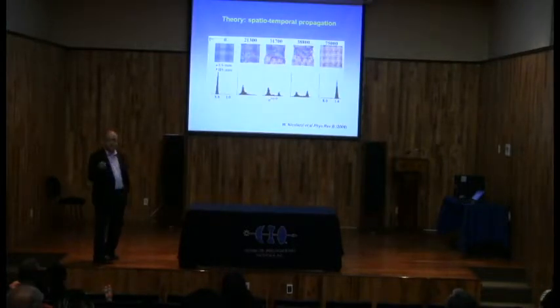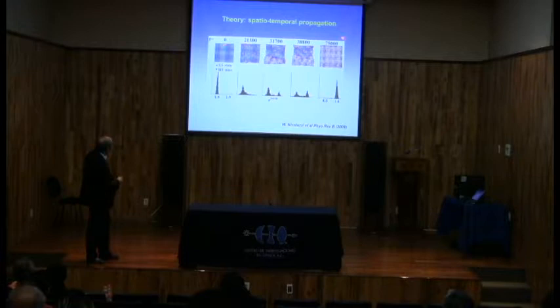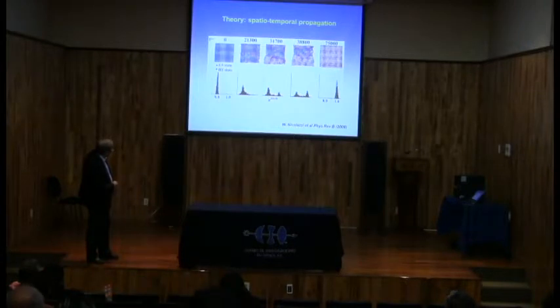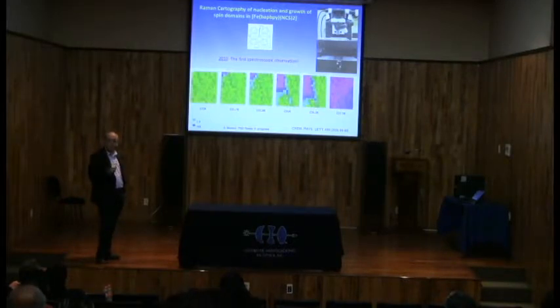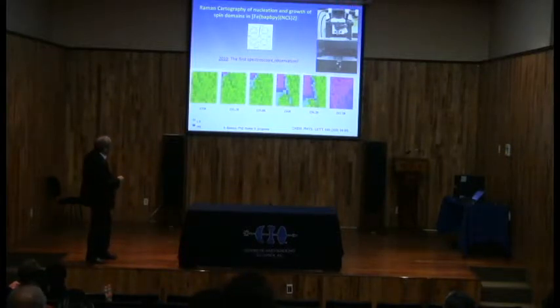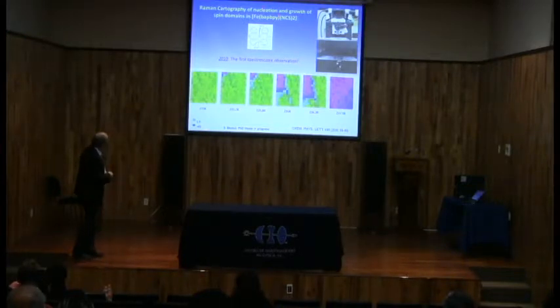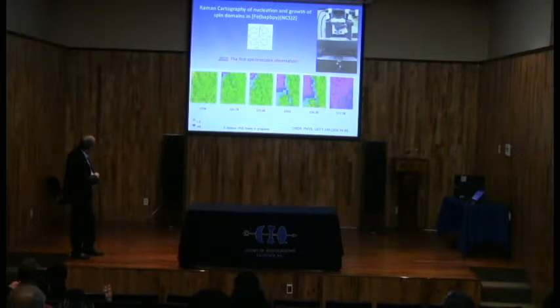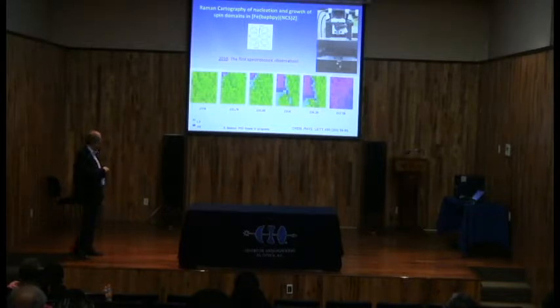Theoretically, if we use the model I have shown you, the model tells us that when you go from the low spin state to the high spin state, you expect to go by a nucleation and growth process. Okay, this is the model. And then we wanted to see this by using Raman spectroscopy, by imaging the crystal with this molecule here. So you see, when we have the low spin state, we take the green color, and when it's the high spin state, we take the pink color.